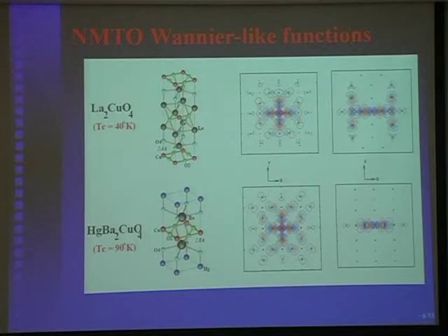So what do we see? As I explained here, you have this x square minus y square, and then you have the antibonding to the neighboring oxygen, which actually proceeds even to farther away oxygen. But what gives this farther away character? To understand that, what we should actually look at is the out-of-plane character. What you see here is again x square minus y square, but you view it from only a certain direction. So you see only the blue lobe of this x square minus y square, which is again antibonding to the oxygen px.